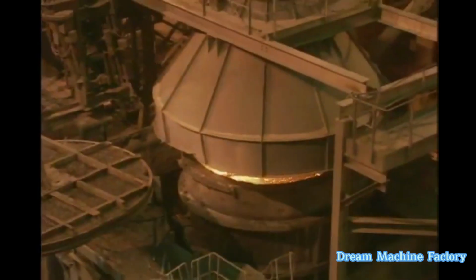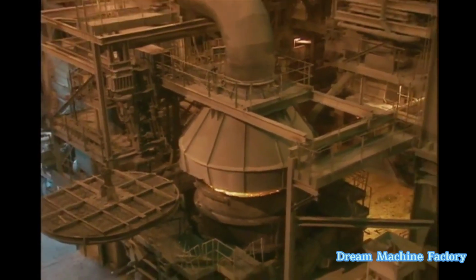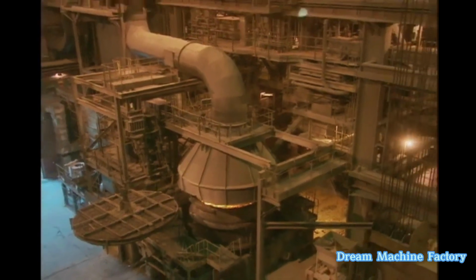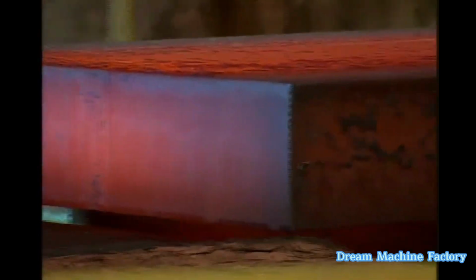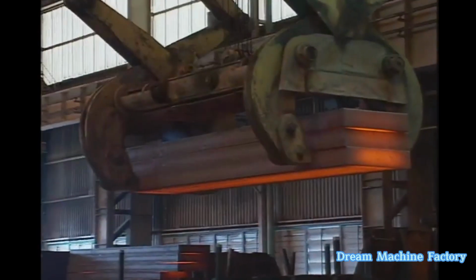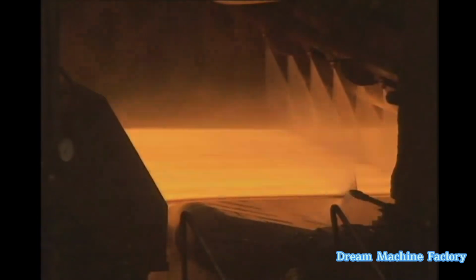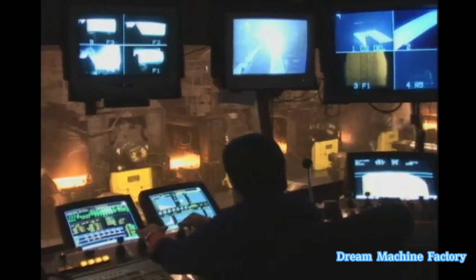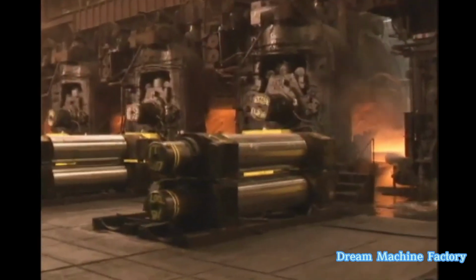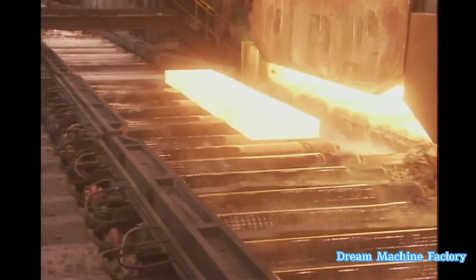These slabs are typically 8 to 9 inches thick and 3 to 5 feet wide. They are cooled to a red-hot solid and cut into sections up to 40 feet long for further processing. The resulting slabs mark the transition from raw materials to semi-finished steel. The semi-finished slabs are reheated to 2,400 degrees Fahrenheit and pass through the hot strip mill, where they are descaled and rolled thinner and longer. This process is completed in finishing stands, which further reduce the thickness of the slabs.